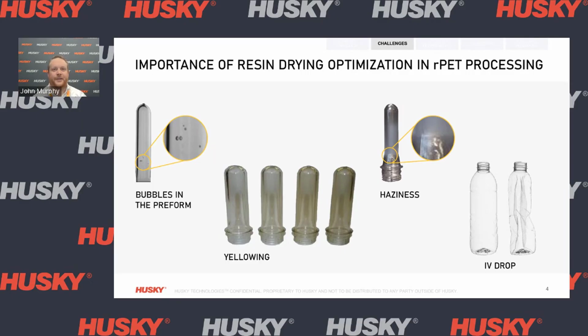This leads to color deviation, potentially high levels of AA, as well as poor blowing behavior. We can also see haziness in the preforms, which is caused by using low temperature resin or having the moisture content too high. This leads to brittle bottles and as well poor blowing behavior. Lastly, we can also see IV drop, which is caused by too much water still trapped in the resin or due to thermal degradation at high drying temperatures or excessive exposure time. This as well leads to brittle bottles and poor blowing behavior. The result of these issues is increased scrap during the blowing process.